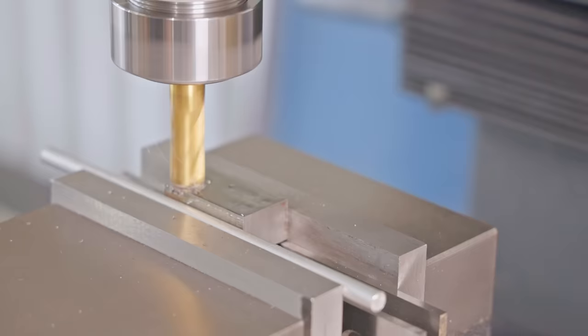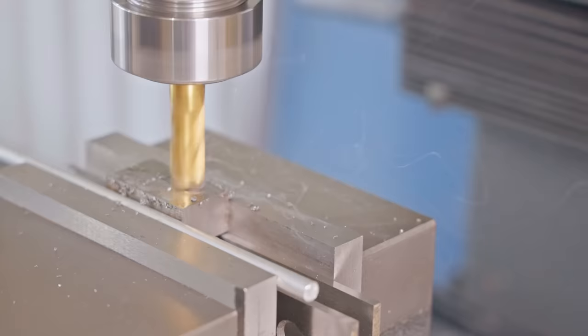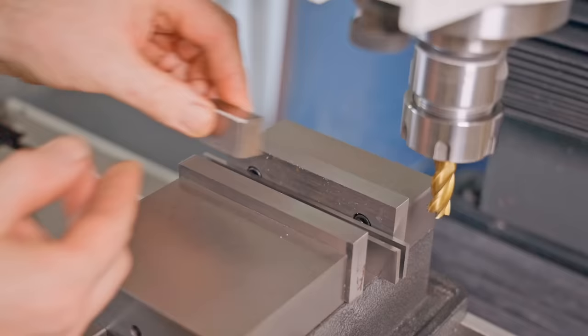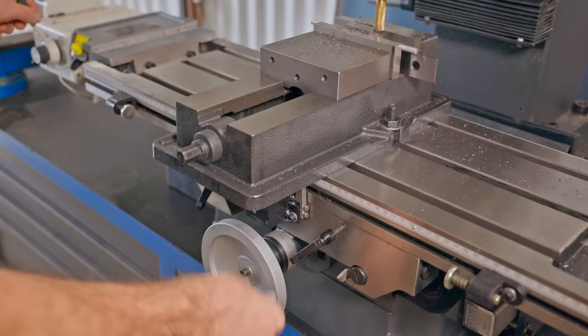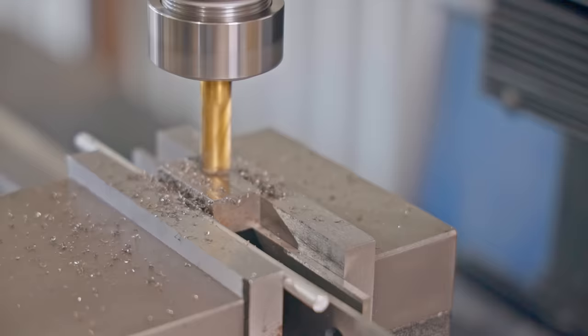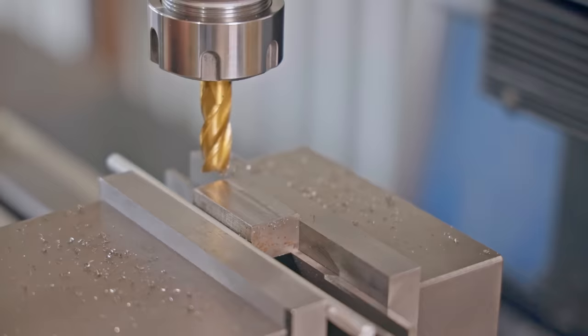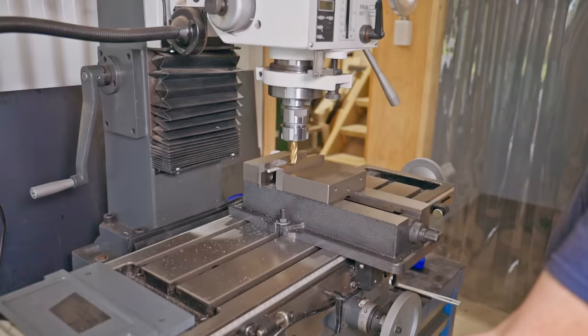The D2 steel is a wear resistant steel that's used for making dies and although I'm not a hundred percent sure I think the D does stand for die. At the moment it's in a soft state allowing me to machine it and when I finish shaping it then I'll harden it. Also another reason why this steel is used for making dies is that it has very little distortion when it's heat treated.